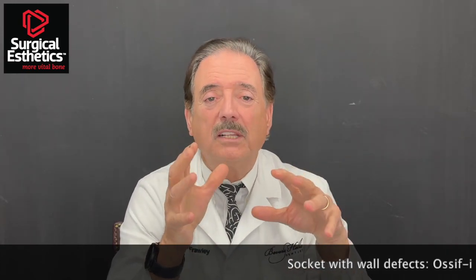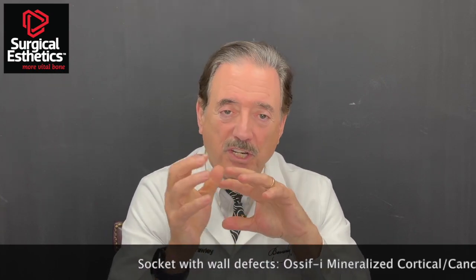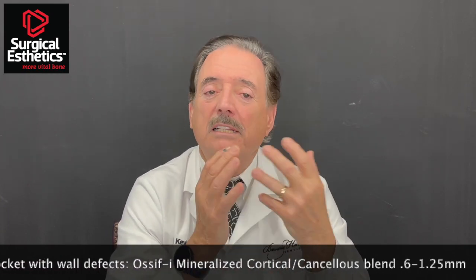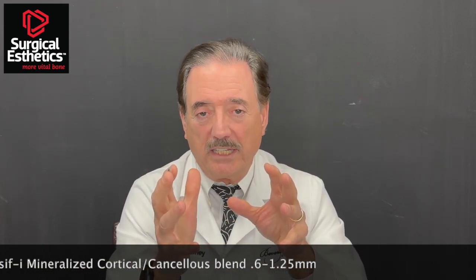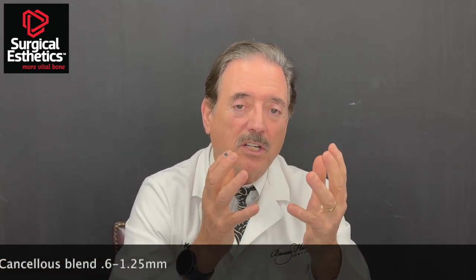If you've got some defects on the buccal wall and you're concerned about really building out that buccal wall, that's a place where I would use the cortico-cancellous because those cortical particles, again, will resorb slower and help to hold that space well.